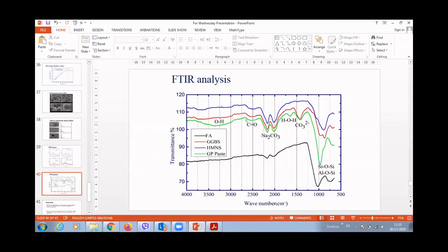To support these results, we did the FTIR to see which kind of bonding exists or is built during the geopolymer process or mechanism. It's clear here, depending on different references, we analyzed the different bonding found. In our geopolymer, shown in green here, there is a huge hump showing the existence of OH bonding, or sometimes water, between wave numbers 3,500 and 3,000. This explains why the strength drops after 90 days. This quantity of water still exists inside the mechanism, and it will evaporate with time, creating microcapillaries, making the paste or the matrix weaker with time.